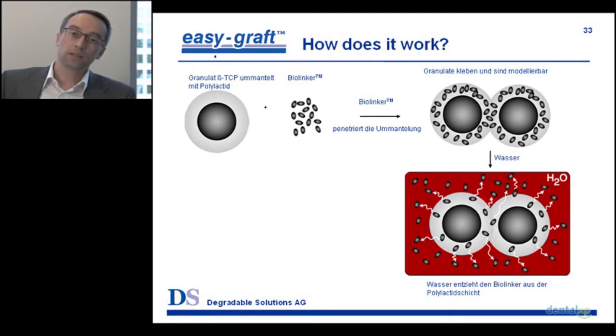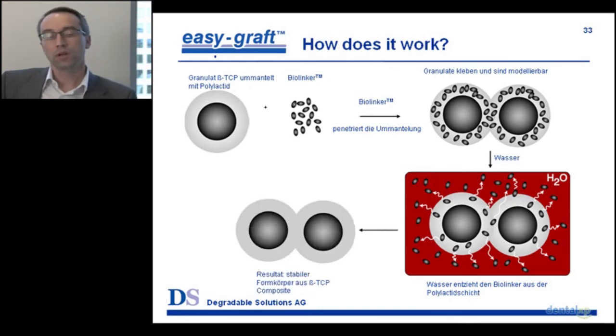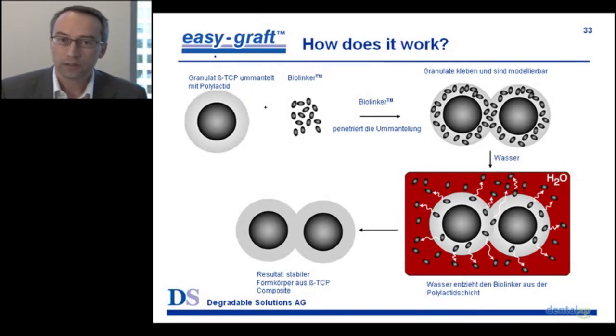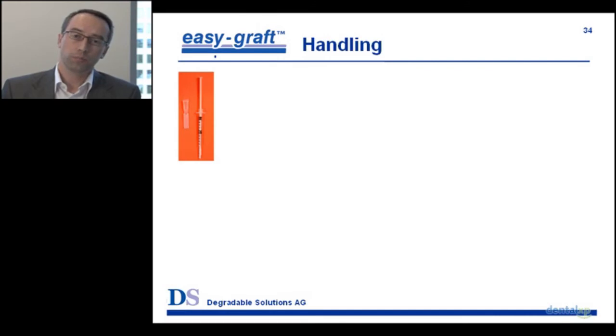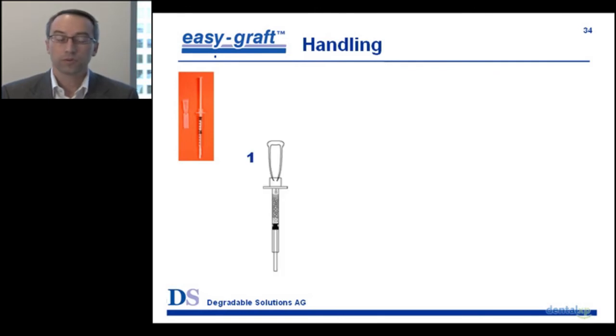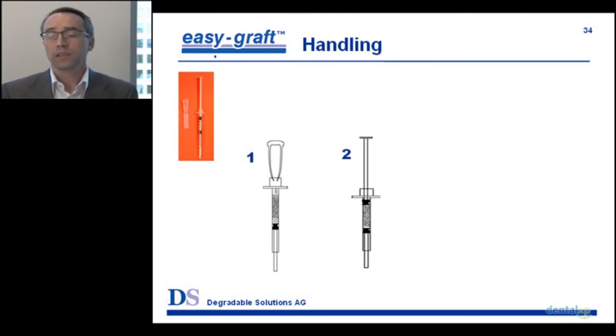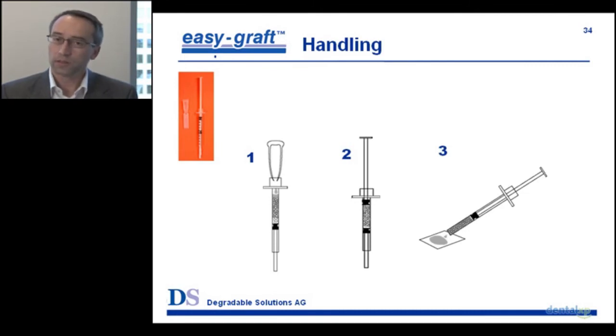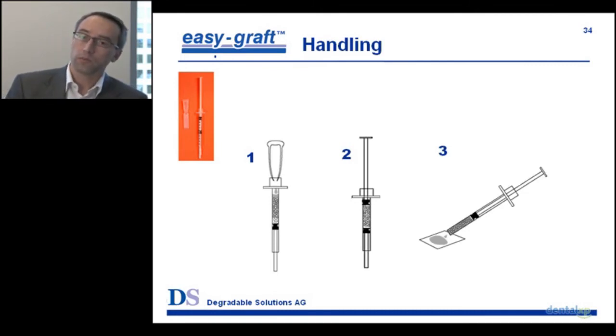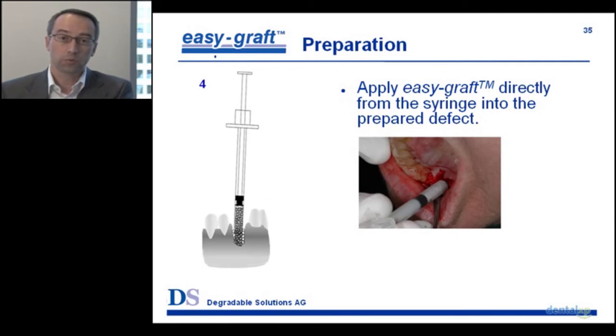Once it is in the defect, you can use a stopper to compress the bone graft into the site and to model it as you more or less would do with a polymeric filling material. And now you have the advantage that you can not only fill extraction sites, but you can put it more or less in any bone defect you have. You can inject it directly from the syringe, mold it, and within 1 minute you have a stable graft there. And the nice thing is, if the biological environment is good, so you have a coverage with the periodontium, for example, you don't need a membrane anymore. So this saves a lot of time and costs for your clinical practice.